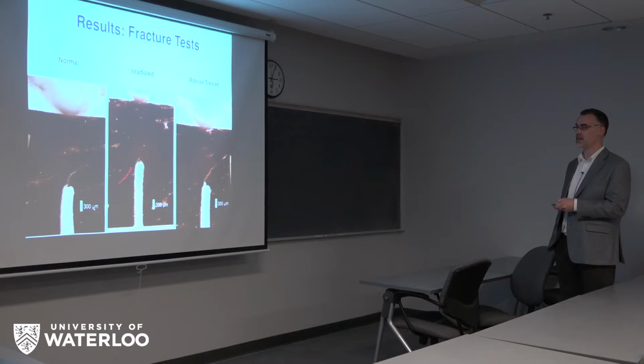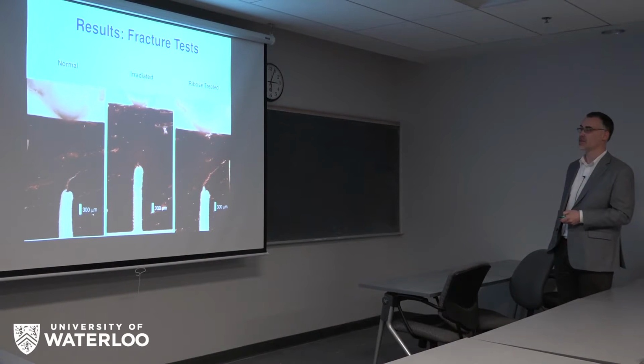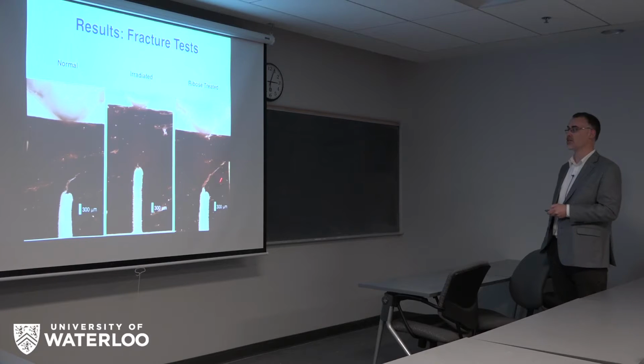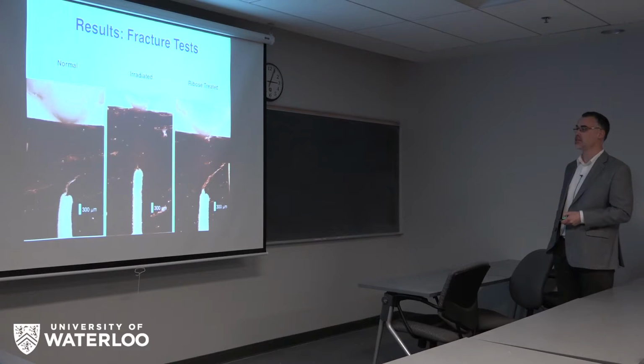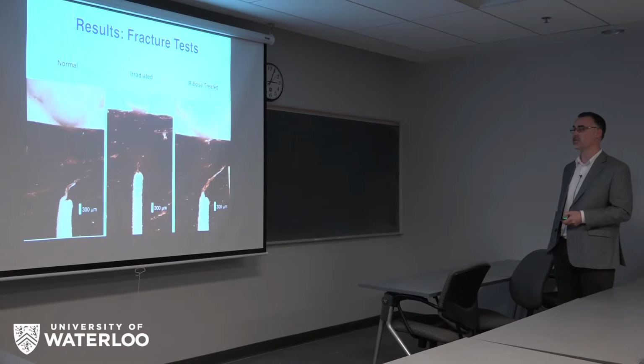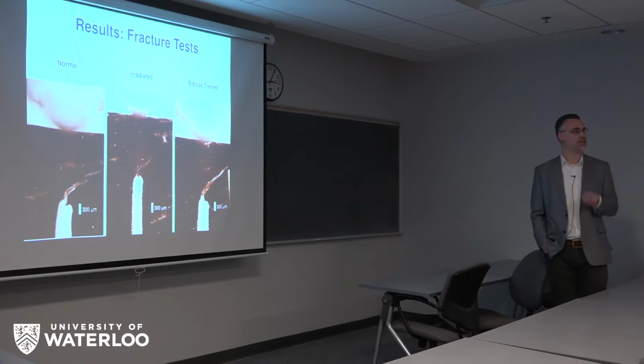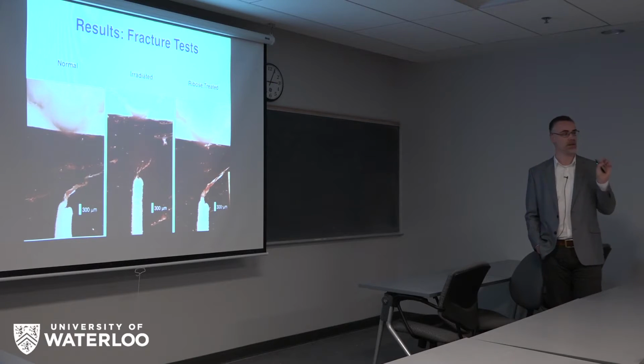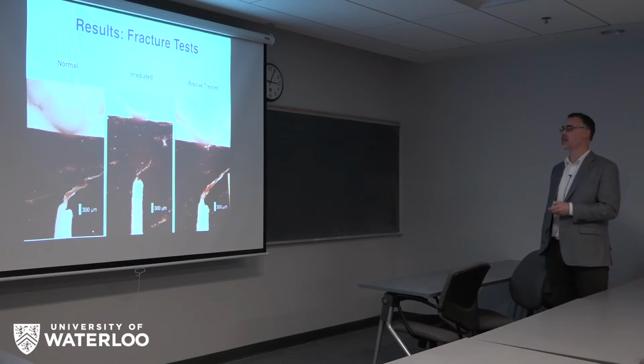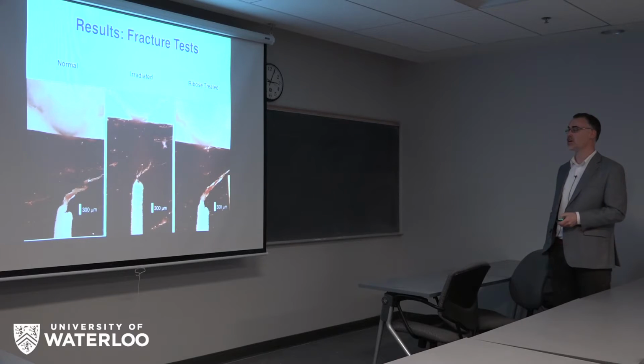Yeah, see that test is done and these two are still going. The normal bone is doing better than the ribose-treated bone, but much better than the irradiated group. And so this was just accomplished with our mechanical testing machine and capturing pictures with our macroscope. And this gives us the information to generate our own JR curves.